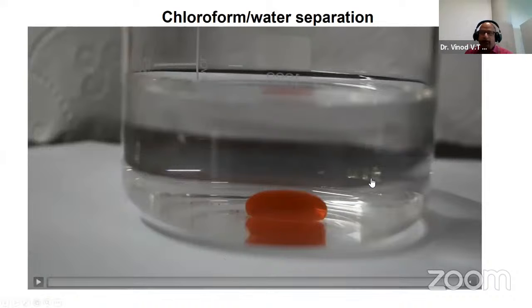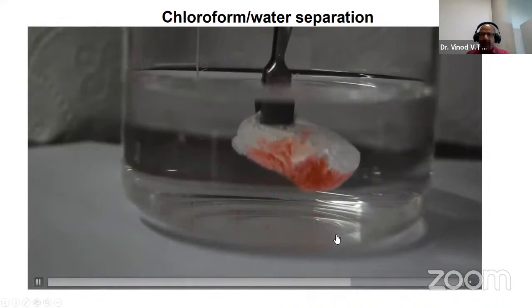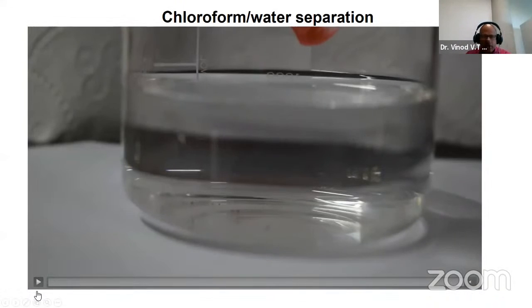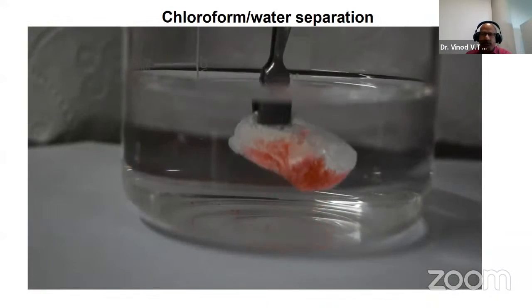In a normal laboratory, you can have a spillage of chloroform, mainly when you work in an organic laboratory or other areas using organic liquids and organic solvents. If you get some spillage on the ground or some places, it can be removed by using this sponge. Here I could show how chloroform can be removed from water. We used some dye to color the chloroform. So this is chloroform in water. How is this chloroform getting removed by this sponge? In a fraction of a second, it gets absorbed onto the sponge.